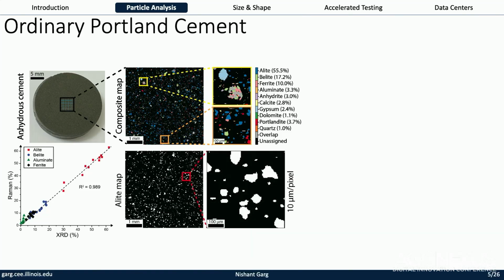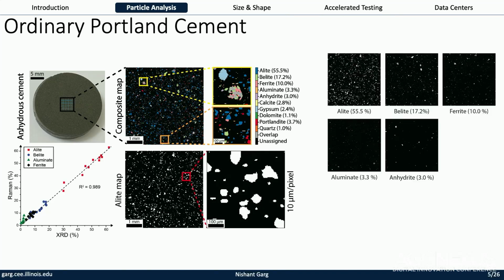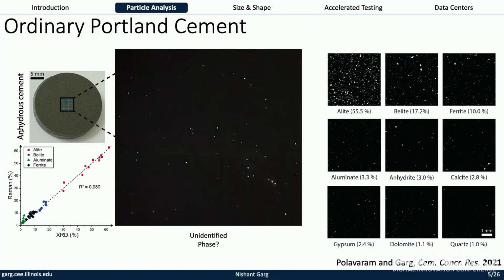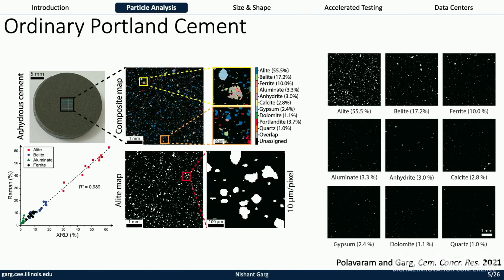We compare this with another technique, which is XRD, X-ray diffraction. This is the gold standard for a cement producer. And when you get a very good correlation between two techniques, it's like getting agreement across two different parties, which is very difficult, but it is happening here. We can then start to see individual grains of a phase at very, very high resolution. Right? We can do this for almost all the phases, even down to something like 1% quartz, which is an impurity, right? So at this point, even the cement producers don't have this level of detail and knowledge that we have, okay?